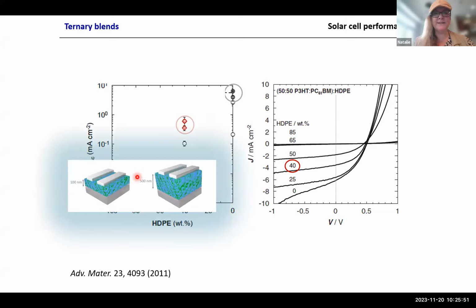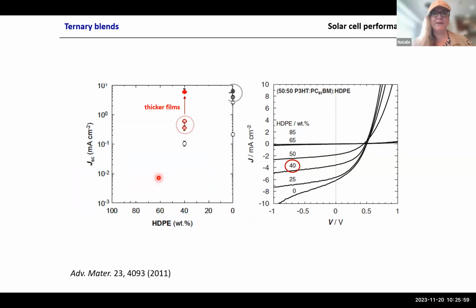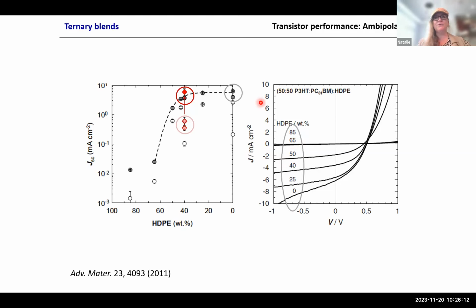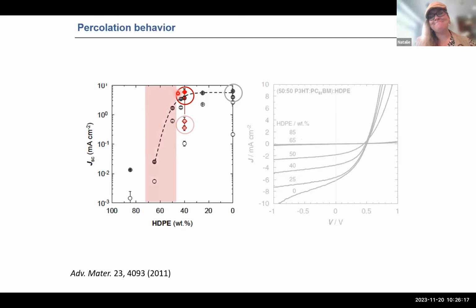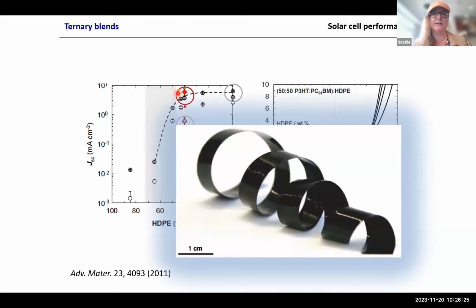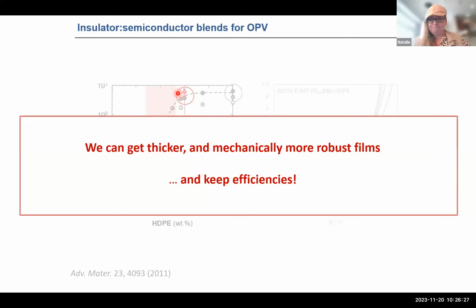So we then made devices that are much thicker, 500 nanometer, which is nice and easy to do once you add the insulator. And when we made films that had the same absorption as the binary blend, we actually got the same JSC. And if we did that for all the different compositions, it turned out we can add up to like 50% of polyethylene and still have working solar cells, but now with mechanical robustness.